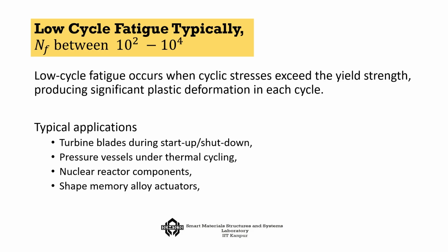Another few important factors for fatigue are low cycle, high cycle, and very high cycle fatigue. So, if the fatigue life, this N_f, is between 100 to 10 to the power 4, we consider this to be low cycle fatigue, which occurs when cyclic stresses exceed the yield strength, producing significant plastic deformation in each cycle. Low cycle fatigue is generally observed in turbine blades during startup and shutdown, pressure vessels under thermal cycling, nuclear reactor components, and a particular actuator which we call shape memory alloy actuator. There also the low cycle fatigue is observed.